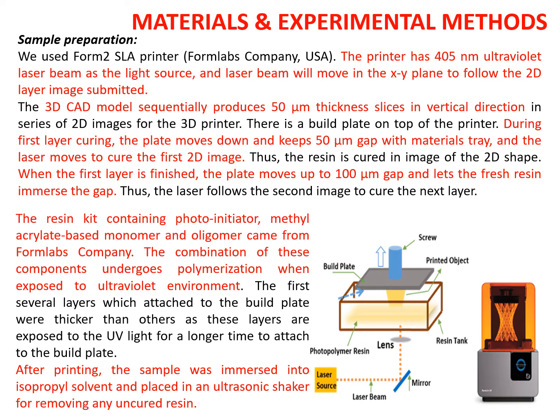Sample preparations all involved an SLA printer, which used a 405 nanometer UV laser beam as the light source. The laser beam moves in the XY plane to follow the 2D layer image submitted. The 3D CAD model sequentially produces 50 micron thickness slices in the vertical direction. During first layer curing, the plate moves down and keeps a 50 micron gap with the material tray, and the laser moves to cure the first two-dimensional image.